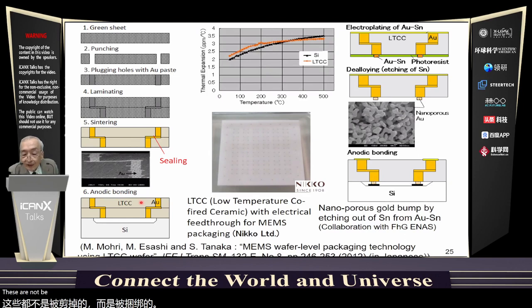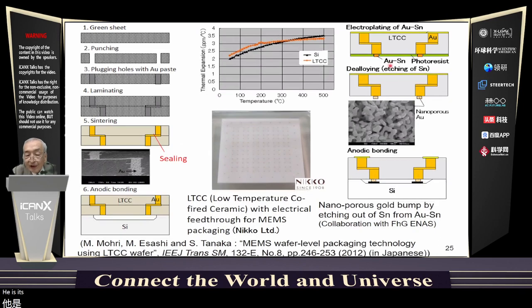This LTCC with a feed through was commercialized by Nikko Limited. Electrical interconnection from the feed through to the silicon is made as shown in the right. First, gold-tin is electroplated and tin is etched out in nitric acid. This makes nanoporous gold, as shown in the photograph. By anodic bonding, we can make electrical interconnection to silicon by using the deformable nanoporous gold.